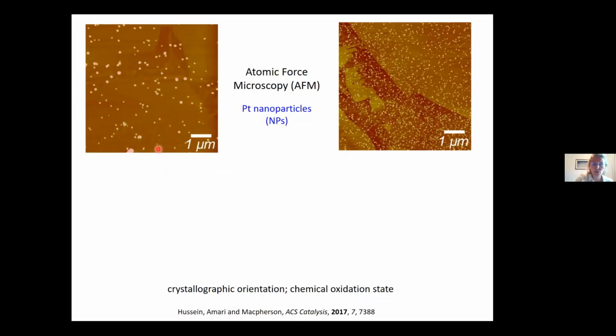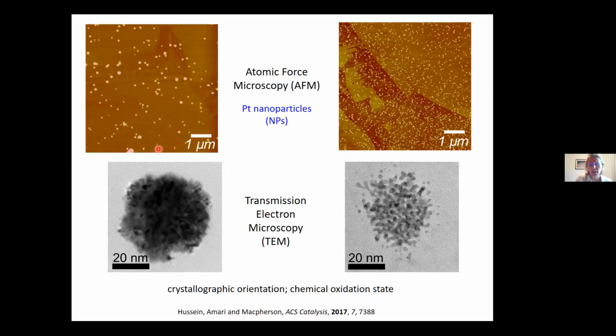But actually when Haytham transferred these particles off the support, so we had to move them off carefully onto the TEM grid and looked at them in TEM, you start to see structures here that are very reminiscent of what John's showing. And the only difference between the deposition conditions for these two images is we use the same overpotential, we use the same time. This is platinum. One was at room temperature and one was at an elevated temperature of about 70 degrees C. But clearly the agglomeration of these structures was incredibly different.